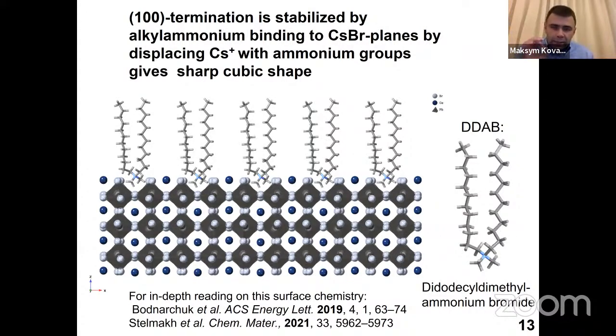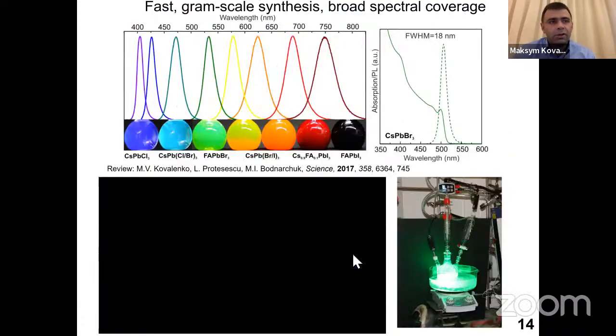So these cationic surfactants or ligands bind to the surface by displacing the surface cesium ion on the 100 terminated crystal plane. And so just replacement, let's say, of 50% of the surface cesium yields such a stable surface facet. Because of this mechanism, your nanocrystal definitely prefers to expose only 100 facets, and therefore you end up with a cubic shape. As a little spoiler, I will show you that you can actually use some other ligands, and therefore you will have different shapes. But in the initial first edition of this material, we had cubic shaped nanocrystals.